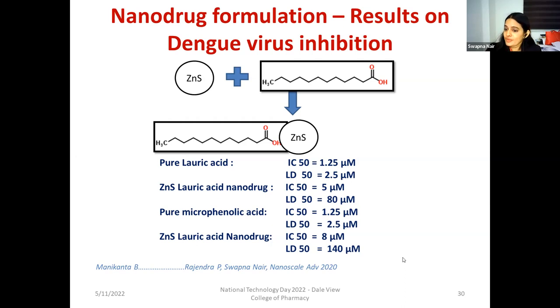So to probe into the mechanism, we have done the drug release kinetics, which shows that a slower and sustained drug release is there for the nanoconjugated systems. This makes the system much more biocompatible and toxicity effects are much less. And the nanoparticle which carried the drug is of 2 to 3 nanometer size, which will be excreted through the urine. So that is another advantage for sub-5 nanometer particles. It's tough for us to make sub-5 nanometer particles, but those are the materials which are useful for these purposes.